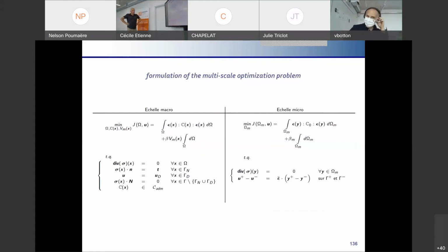From a mathematical point of view, it is possible to write, in terms of Lagrangian minimization of functional, the optimization at the coarse scale and the optimization at the fine scale. It is not exactly the same problem. On the left is a standard optimization of the coarse scale, in terms of Young modulus and density. So you can see in the Lagrangian that you have something close to the elastic energy, and here an optimization on the volume of the material, and you can define a parameter if you want to have a specific compromise between elasticity and density with the reference problem on the coarse scale.